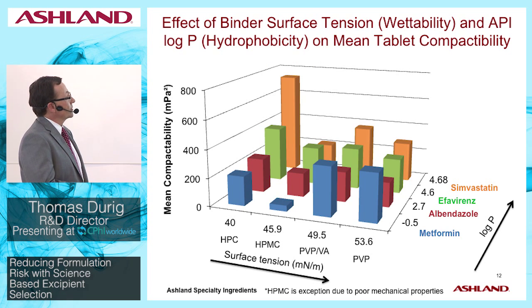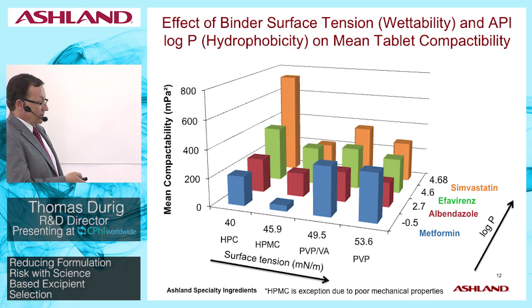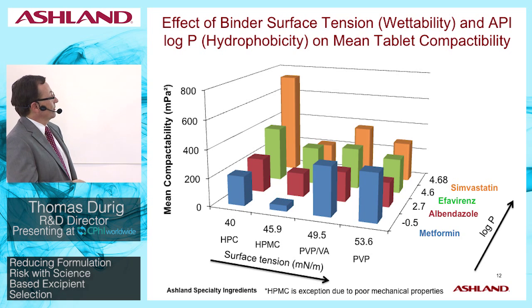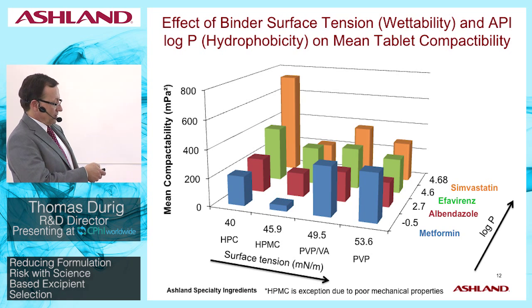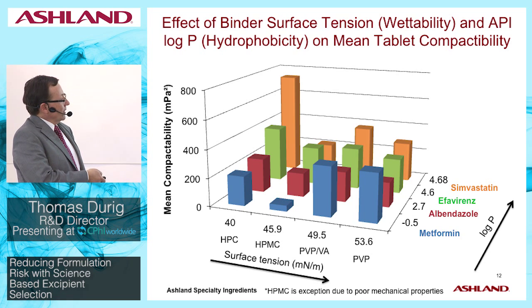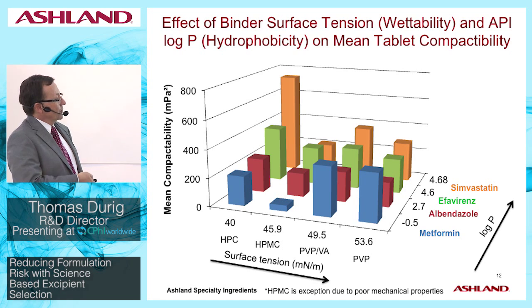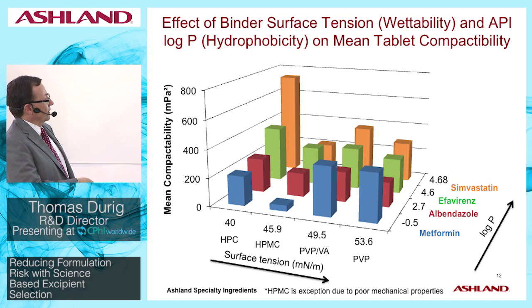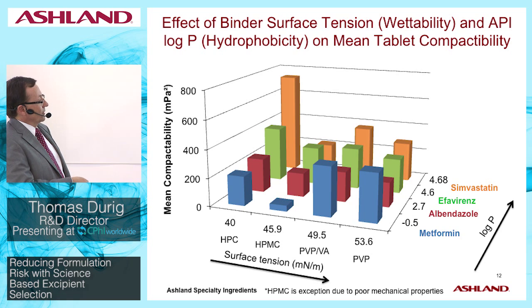Using this approach, our scientists have conducted some studies where we systematically varied the surface tension of the binder solution by choosing different binders that give different surface tensions, and looking at this for different hydrophobicity APIs, basically drug molecules with different hydrophobicity. In this case, we measured the hydrophobicity as the log P.